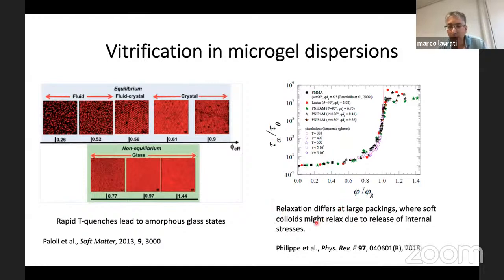And actually, recent works from people in Montpellier also showed some interesting things, like the fact that at least for some of the microgels, the transition actually shares common behavior with harder systems like the PMMA, at least until you enter into the glass state. For larger values, when you enter really into the glass, there are differences, especially in the aging behavior, which is really peculiar in the soft systems, and it's related in part to the fact that you have soft particles which can release stress when they are compressed, basically, against each other.